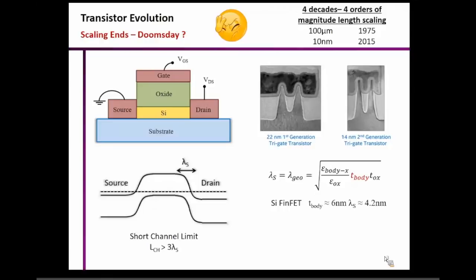Now, what has happened over the last decade is that we have exhausted the t-ox and epsilon-ox scaling because we are really using ultra-thin high-K dielectric material. So that space has been pretty much exhausted. What is left is the scaling of the body thickness t-body, because epsilon-body is the dielectric constant, and as long as you're using silicon, you have to deal with that number. The current technology uses a silicon film of about 6 nanometers. For that thickness, you can scale the devices down to about 10 nanometers. But what happens beyond that?